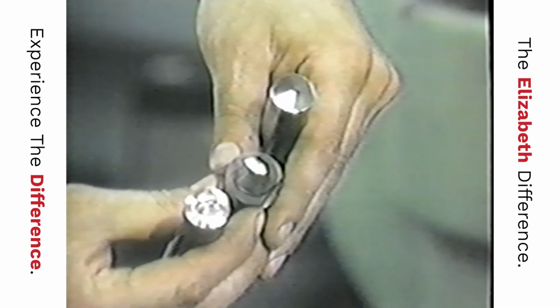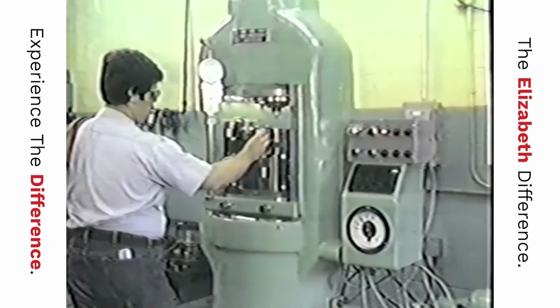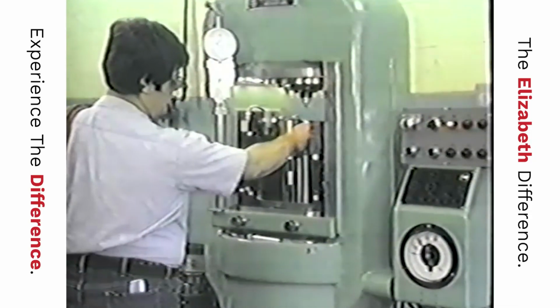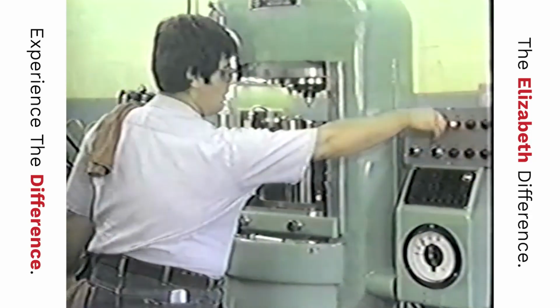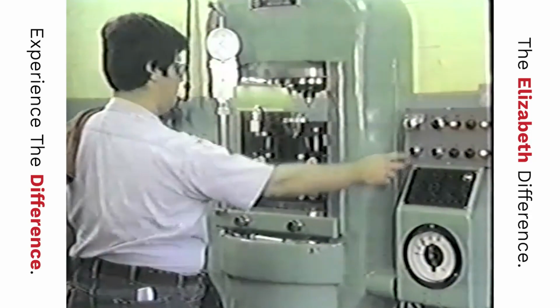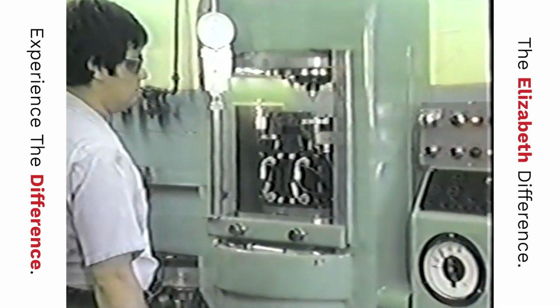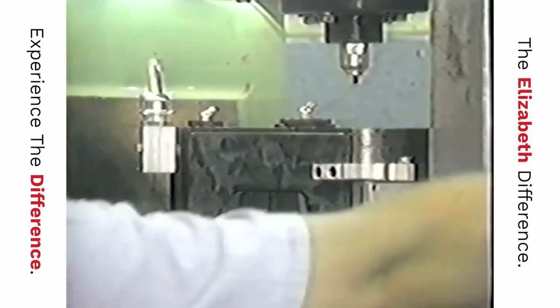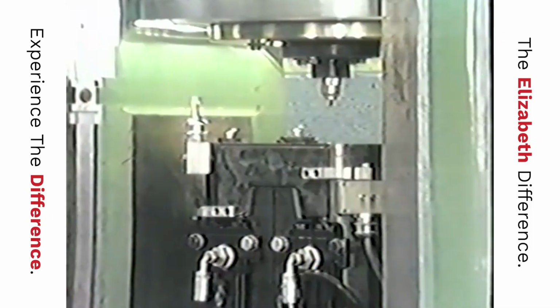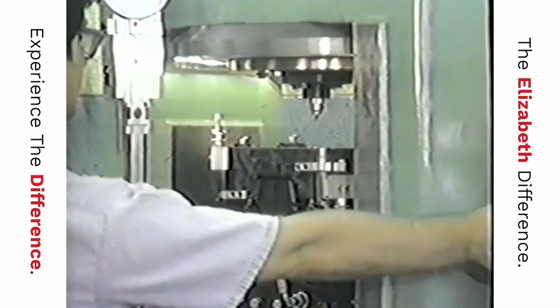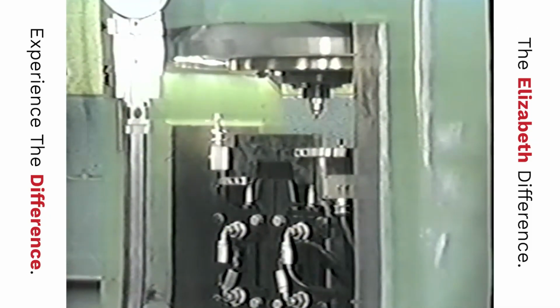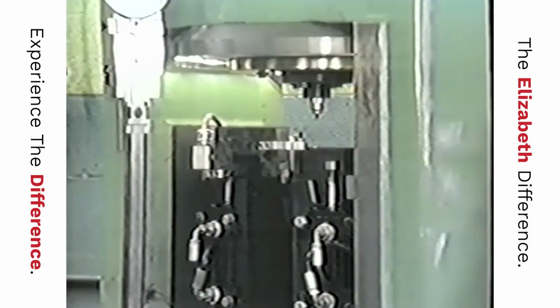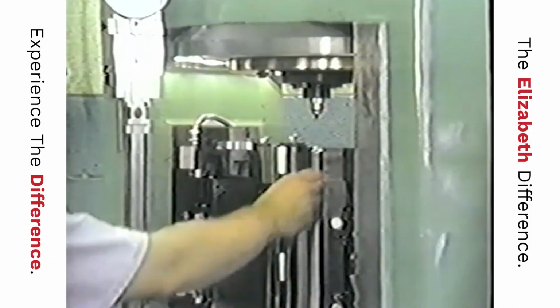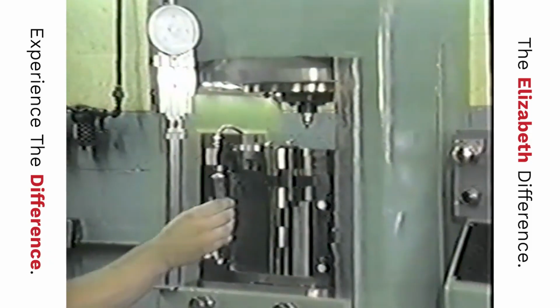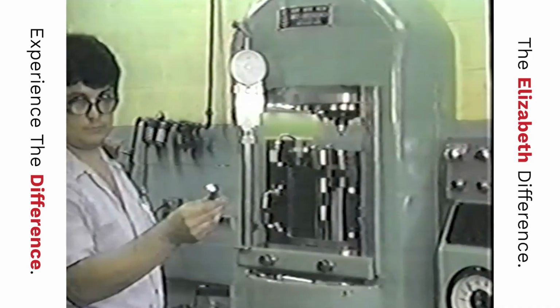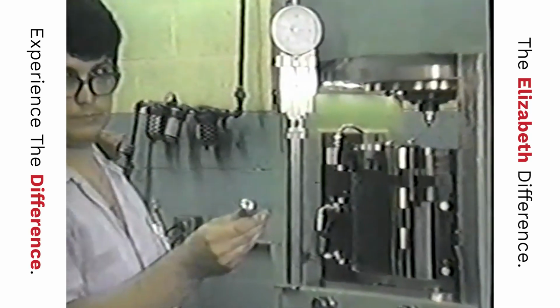The final hobbing procedure is very simple because all the precision alignments have been built into the specially designed nests and fixtures of the hobbing press. The hob is fastened into place at the top of the press, and the punch blank is placed into a contained fixture that will hold it in position while the hob is pressed into the blank under hydraulic pressure. These pressures can range between 50 to 200 tons, depending upon the punch tip size and the type of steel used.